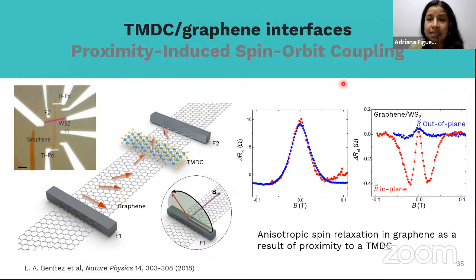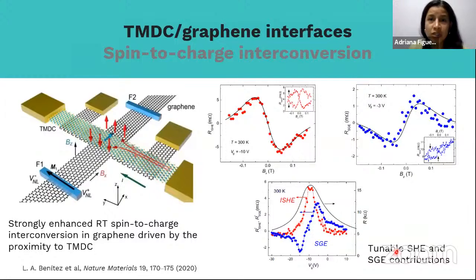In this case, this is also relevant for spin-to-charge interconversion at that interface, because these are also results by people in our group, where they observed tunable spin Hall effect and spin galvanic effect contributions at the interface of these systems, which is very relevant for spintronic applications, where you can have control of the spin-to-charge interconversion at those interfaces.